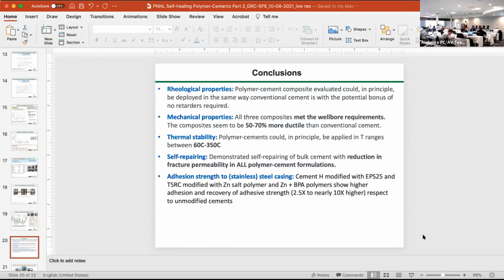Real quick question. I might have missed it, but do you have a 35% silica in your cement? We have a 70-30 formulation, 70% cement and 30% pozzolanic material, based on dry mix. That's just a typical formulation for wellbore cement, cement H or cement G.